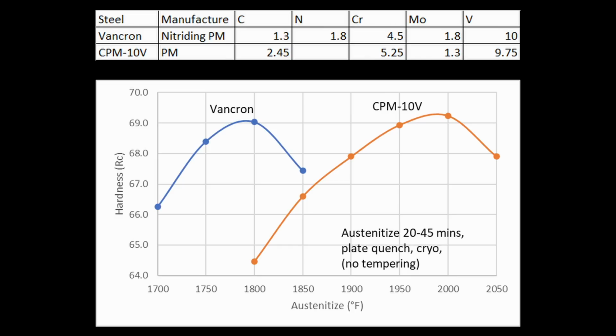So what's going on with this one? Well, this steel is not designed to have nitrogen in solution. The nitrogen is not added for hardness. It is added to form a vanadium carbonitride rather than a vanadium carbide. So the hard particles are made up of carbon and nitrogen instead of just carbon. And that's added for a thing called adhesive wear. We talked more about this in my other article video.